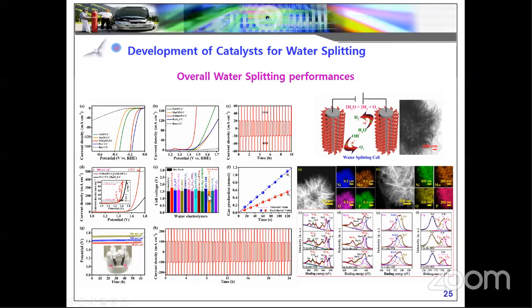And when we want to prove our materials towards commercialization, then we need to prove the theoretical value of the hydrogen and oxygen evolution. From the studies, you can see the hydrogen and oxygen evolution is almost equal to the theoretical value. And we also tested with different currents in the chronopotentiometric test, and our catalyst is stable for almost 60 hours at all different current densities.